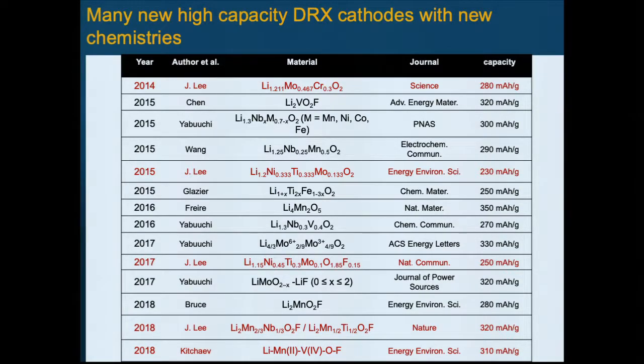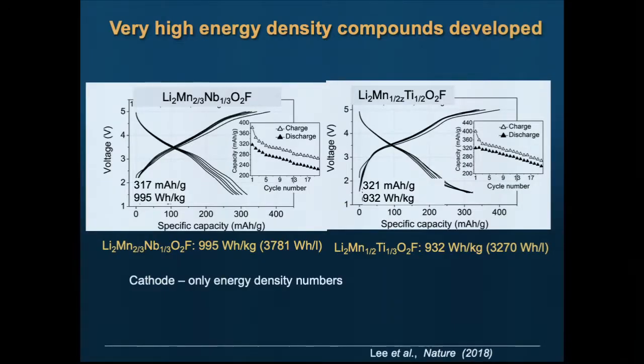Since then, lots of people have appeared on the scene, made all kinds of materials with very different chemistries, and if you look at this, this has a lot of chemistry that is not present in today's lithium-ion materials. We use molybdenum, chromium, vanadium, niobium, titanium. So in some sense, we've really unlocked the periodic table here by doing this.